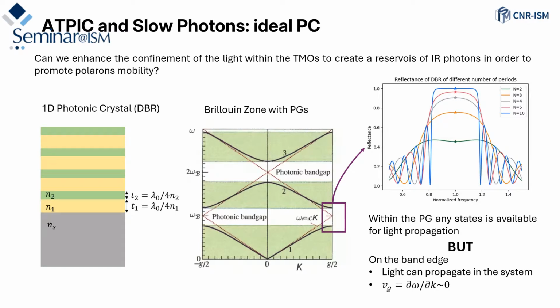Just consider a very easy photonic crystal, which is a DBR in one direction. Then, of course, this kind of photonic crystal has a band gap, which is revealed by the enhancement of reflectance in some particular area of the spectrum. And this means that the photons in this region do not access the system because they are all reflected. But if we are near the band gap, where the transmission is higher, in these regions you should have light that can propagate in the system and has a very low group velocity.